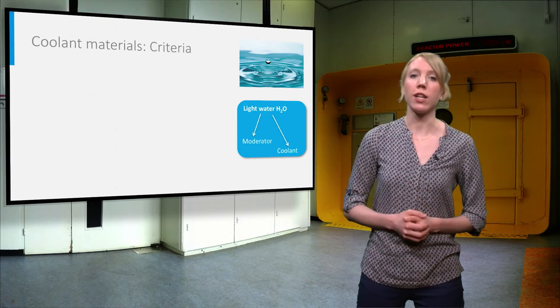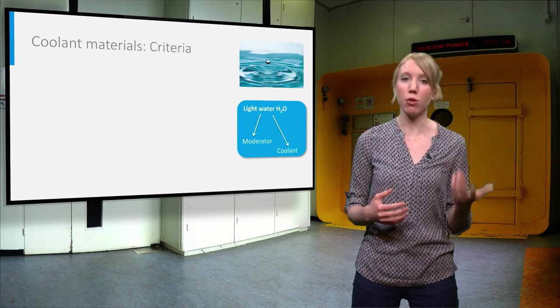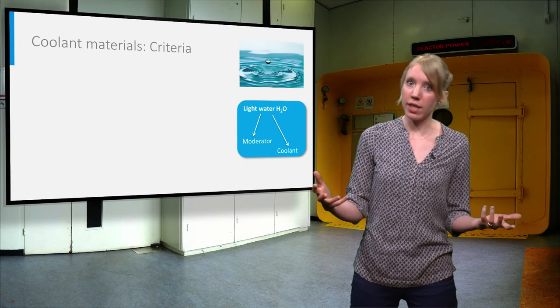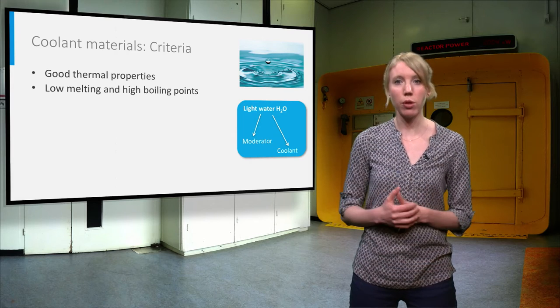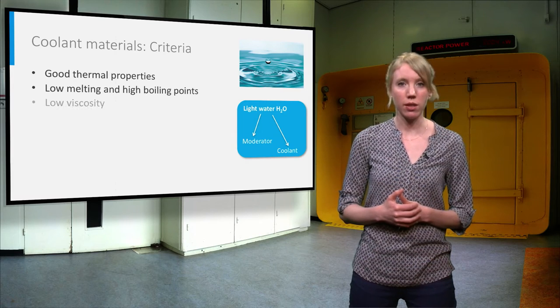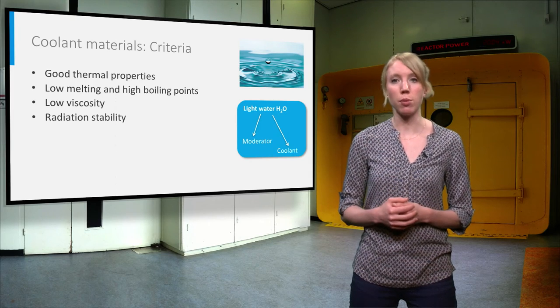The coolant allows the extraction of the thermal energy generated in the fuel assembly. Ideally, the coolant should have good thermal properties, low melting and high boiling points, and a low viscosity. It must show radiation stability and low neutron absorption.